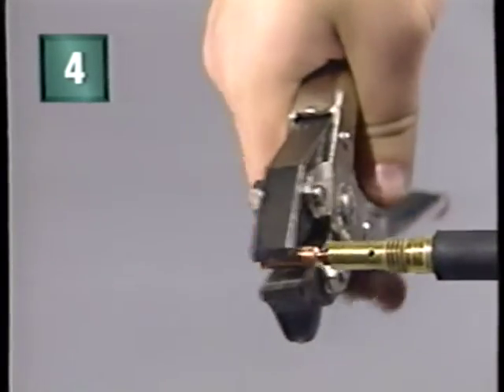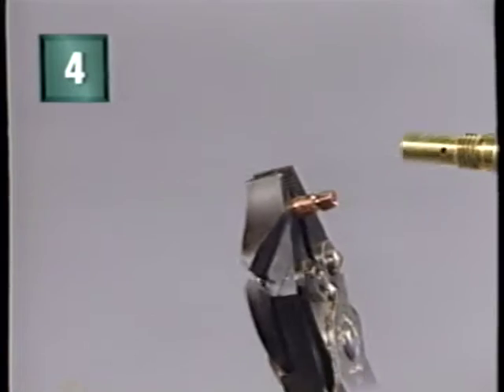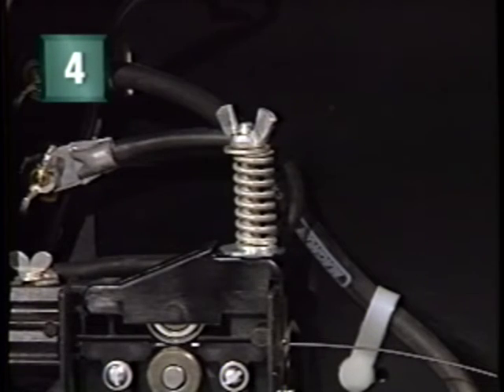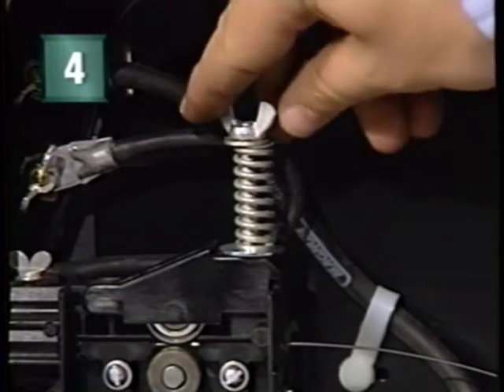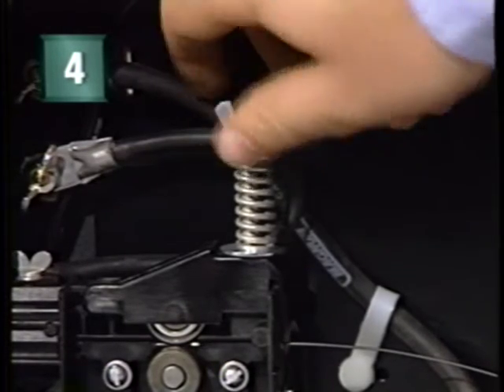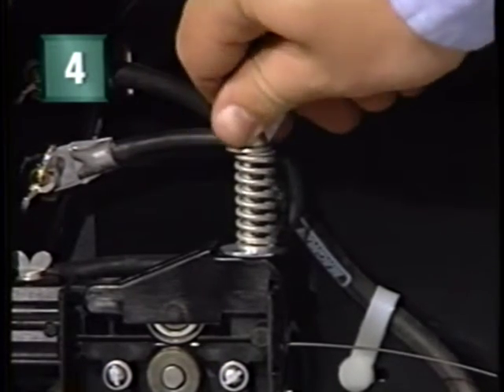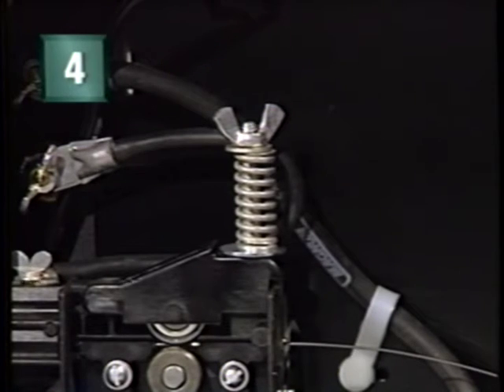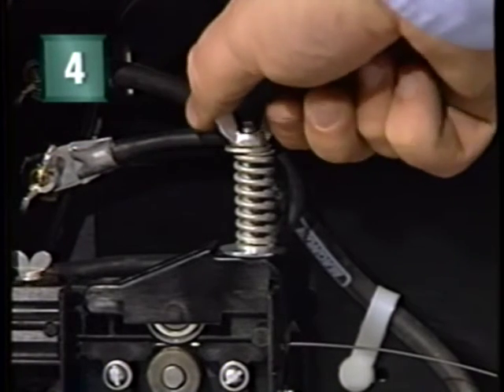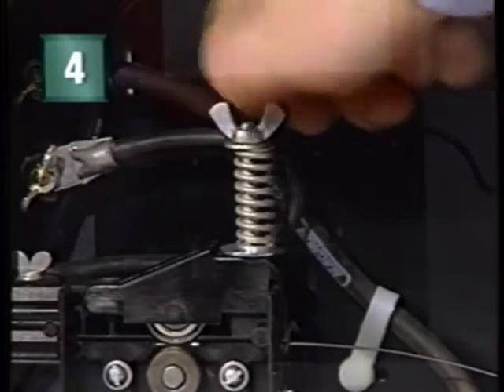Now remove the contact tip at the end of the gun cable assembly. This idler pressure adjustment wing nut is usually set for about mid-position on the pressure arm threads. Slightly less pressure may be needed with .023 to .025 wire. If the drive roll slips, increase the pressure until slipping stops. If the wire becomes flattened excessively, turn the pressure adjustment counterclockwise to reduce the distortion.